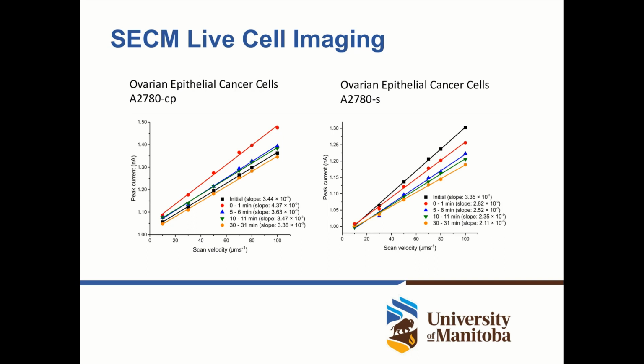Now let's have a look first at the black curve. You find the black line, which is right in the center there, and this is our initial slope. These are the cells before we treat them with carboplatin. Now we are exposing these cells and carrying out these line scans every 5 minutes. You see the very first line scan that we do immediately after exposure represents a change of slope. The slope increases before it then relaxes back, and it's very stable over a time period of 30 minutes. When we look at the susceptible cells on the right-hand side, however, you see that after exposure, this slope gradually decreases. So this is already a qualitative appreciation of the differential behavior between resistant and susceptible cells by electrochemistry.